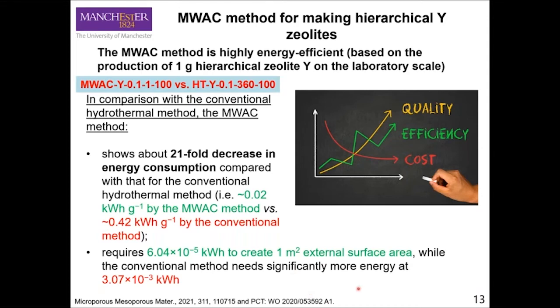And also, if we consider the external surface area as the key criterion for the size of the mesoporosity in a hierarchical zeolite, we found that for creating 1 square meter of external surface area, the energy required by the new method is much lower than the conventional one.